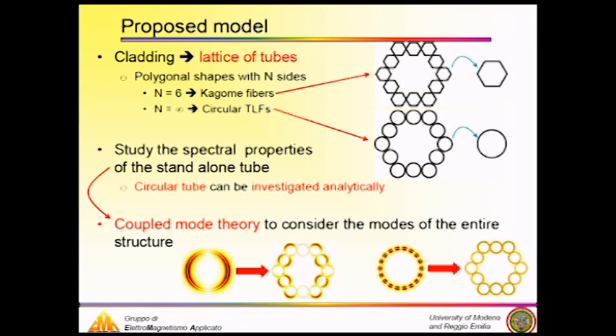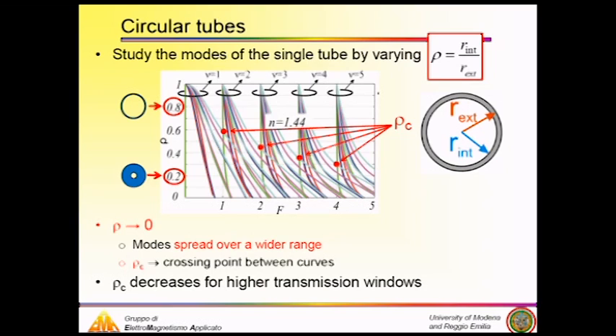So our idea is that we can start from considering the standalone tube itself and then move to the microstructure cladding by using the coupled mode theory. Of course, what is interesting in our solution is that the circular tube can be investigated analytically. So carrying out calculations, we have considered what happens to the modes of the standalone tube when changing the rho parameter, which represents the ratio between the internal and external radius of the standalone tube. As we move from 1 toward 0 rho values, which means we are dealing with thicker tubes, the modes of the tube spread over a wider range. And for each transmission window, here, here, and here, there is a critical rho value at which these curves cross each other.